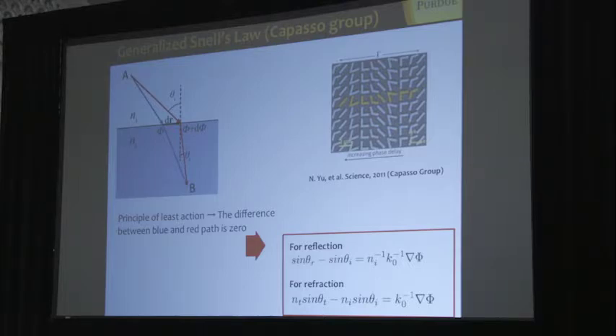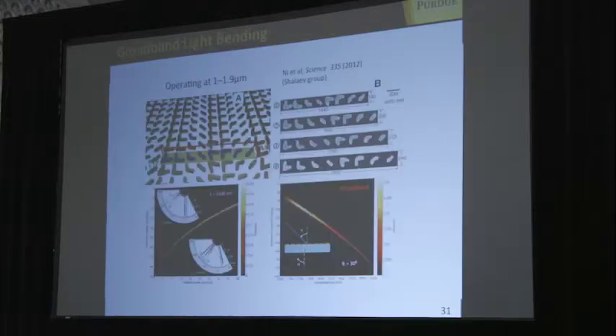And as a result, you modify Snell's law. You have this additional term, gradient of phase, which could be as large as any other terms in this equation. So you have this possibility to really design and engineer the way light goes through the interface between materials. That's a very simple, straightforward idea, well known for the microwave range, microwave antennas, but somehow never was employed in full measure in optics.